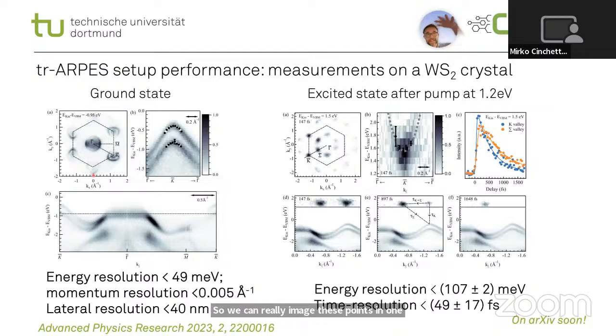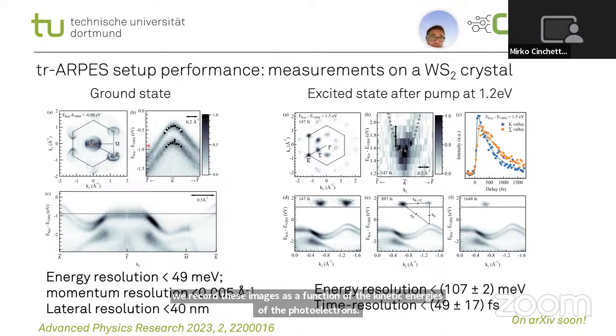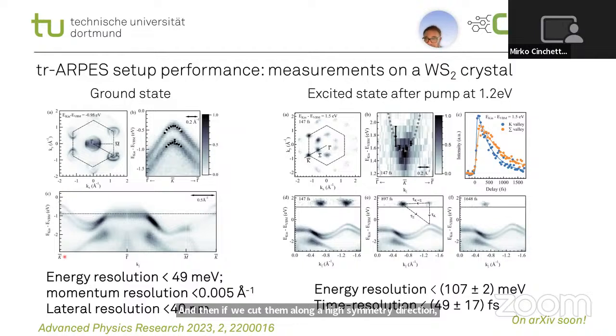We collect then this data cube of so-called momentum maps. So we record these images as a function of the kinetic energies of the photoelectrons. And then if we cut them along a high symmetry direction, what we obtain is the band structure of the material. So here you have the momentum along one particular high symmetry direction. And here is the binding energy of the electrons. Zero here is the valence band maximum. And what you see here are then the bands of tungsten disulfide. These two spin-orbit split bands are actually quite famous.